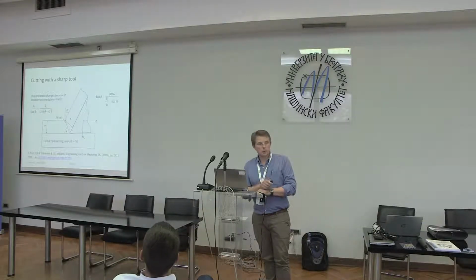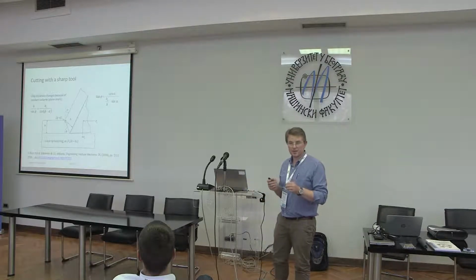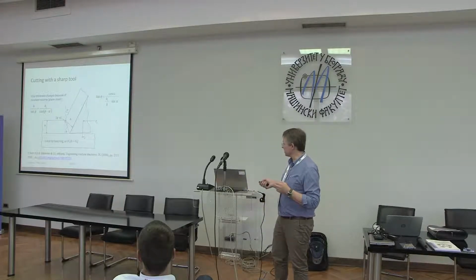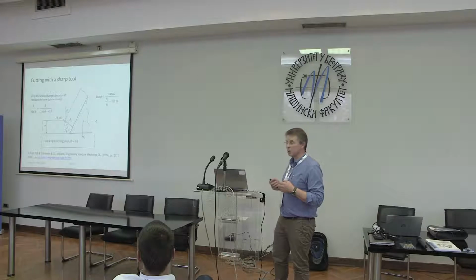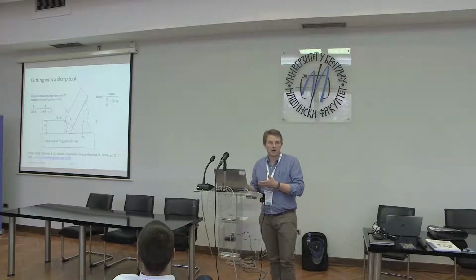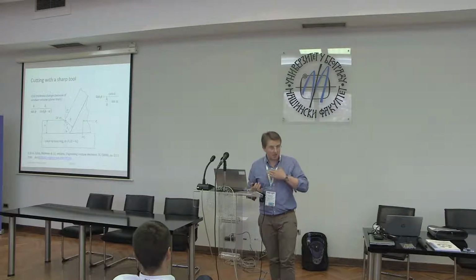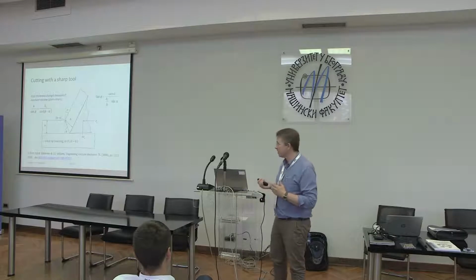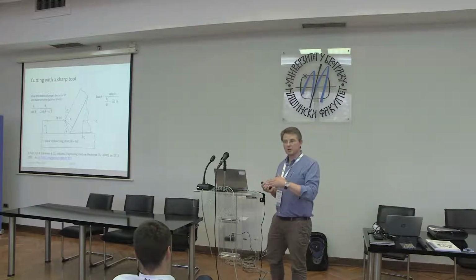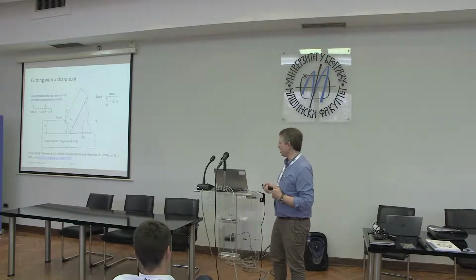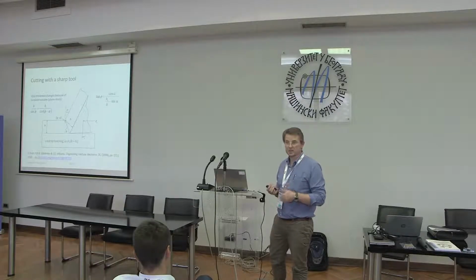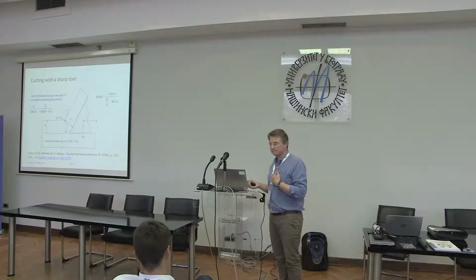And a good way of doing these experiments is to vary the depth of cut. So what we do, for example, is to vary H. So you might have a minimum H of about, I don't know, depends what you can manage with your system, but in our case it was about 25 microns. So we cut a slice about 25 microns off, and we systematically increased that thickness, maybe a factor of 10 or 20 to up to about 0.5 millimeter.